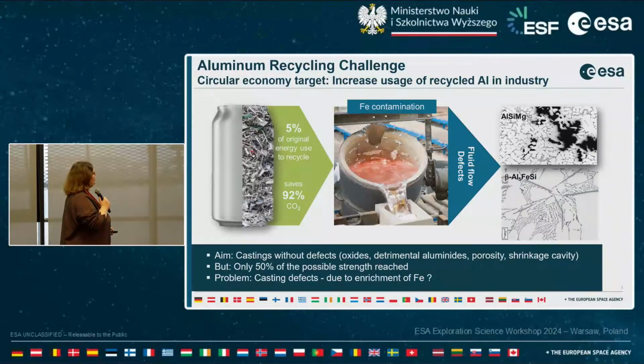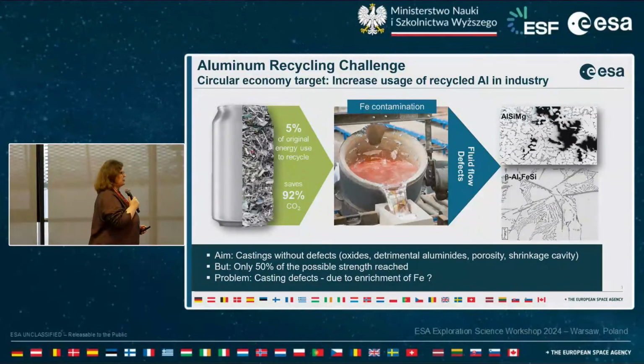And when you cast parts from recycled alloys, it's observed that sometimes only 50% of the possible strength of the cast part is reached. And the reason why: in foundries, the element iron is suspected to be the origin of a lot of casting defects like shrinkage, porosities, and so on, because during solidification of such types of alloys, so-called iron-containing intermetallic phases like this beta phase, which looks like needles in 2D, are solidified.